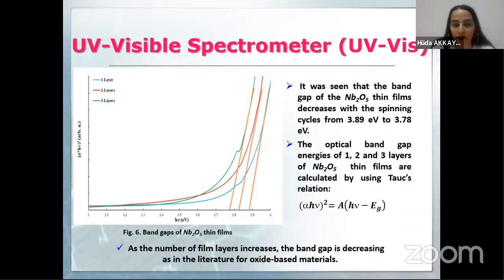And figure out the band gaps of niobium pentoxide thin films. The optical band gap energies of 1, 2, and 3 layers of niobium pentoxide thin films are calculated by using Tauc relations, and it was seen that the band gap of the niobium pentoxide thin films decreases with the spinning cycle from 3.89 electron volt to 3.78 electron volt. And then we conclude that as the number of film layers increases, the band gap decreases, as in the literature for oxide-based materials.